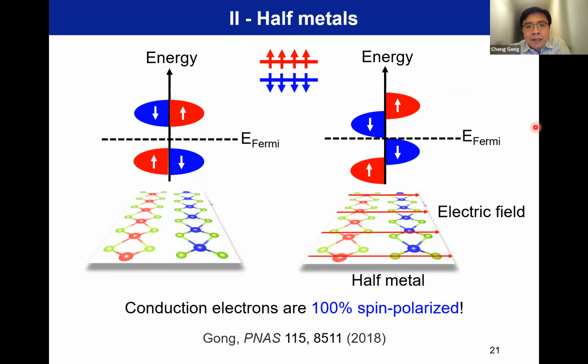Okay, that's a good question. As I introduced the concept here, in this part of the work, we did not aim at using a small voltage to realize this effect. The mechanism here is that you have an electric field, which gives different electrostatic energy for the two layers. So one will be pushed down, one will be lifted up. In the end, you will always merge them, but you may need a large voltage.